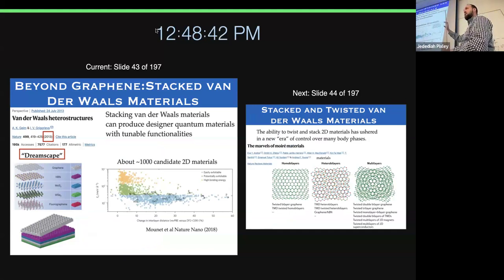So they find materials that are effectively 2D. They find the binding energy, which can be broken by the Scotch tape adhesive scale. And there are about 1,000 material candidates. So I'm only talking about graphene and a couple of TMDs, but there's a huge number of possibilities here. And my group right now is actively trying to predict what types of materials to stack and twist in the future. That requires machine learning and all sorts of sophisticated methodologies that we're trying to develop.